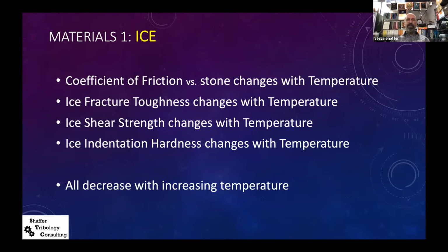Well, the coefficient of friction of the ice versus the stone seems to change with temperature. This has been measured. The ice fracture toughness changes with temperature. And this is a mechanical property that we can measure. The shear strength changes with temperature. The indentation hardness changes with temperature. All these things decrease with increasing temperature. And that's important because we set the temperature of the ice when we're making the ice and keeping the ice house at one temperature, but the sweeping in front of the stone by virtue of friction warms the ice, and therefore we'll see perhaps the result of those changing properties.